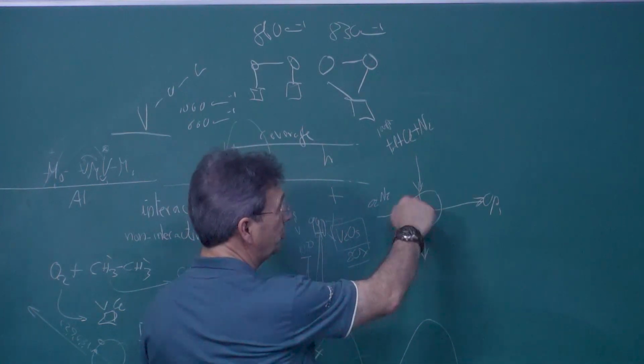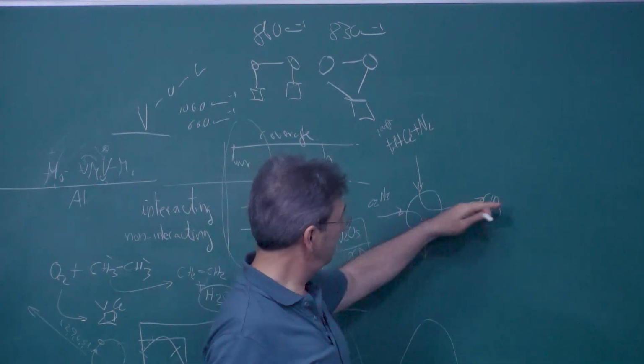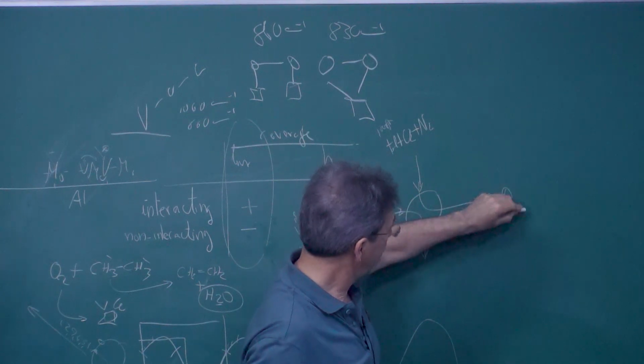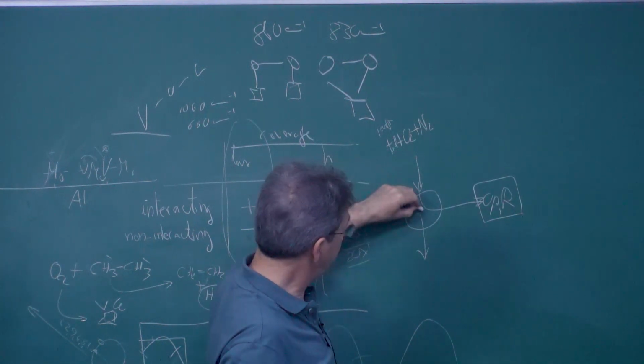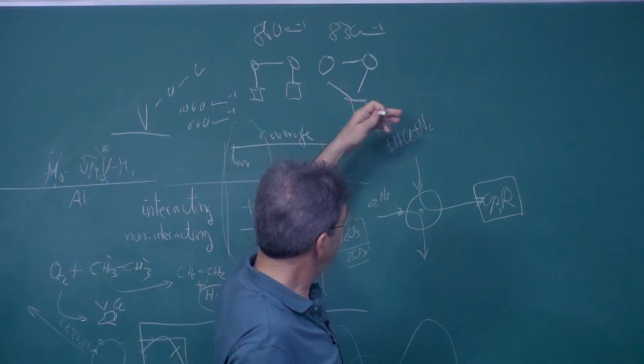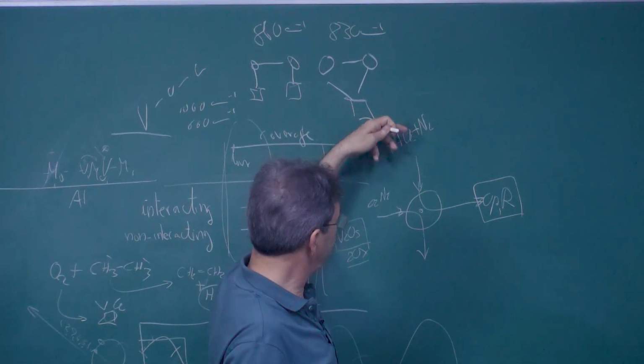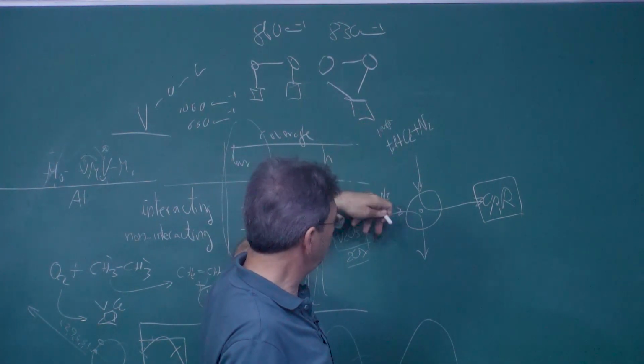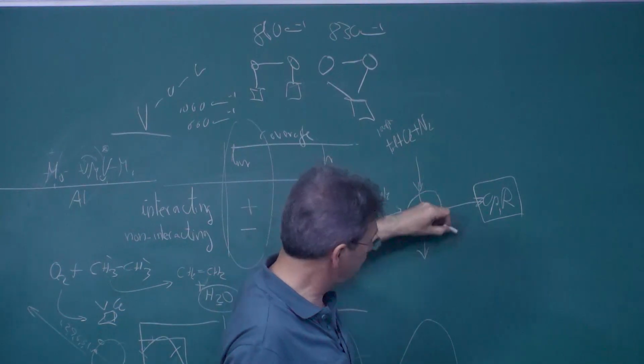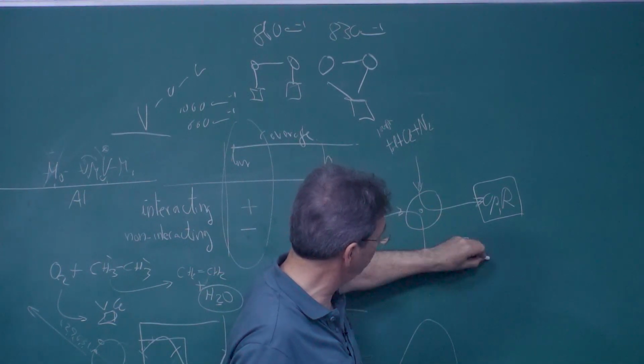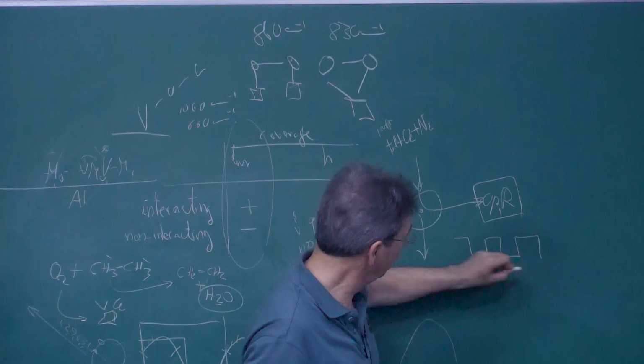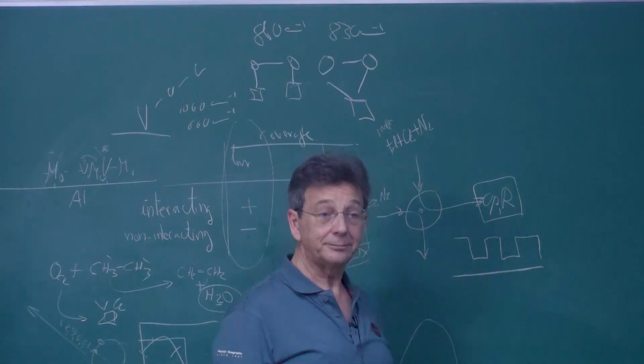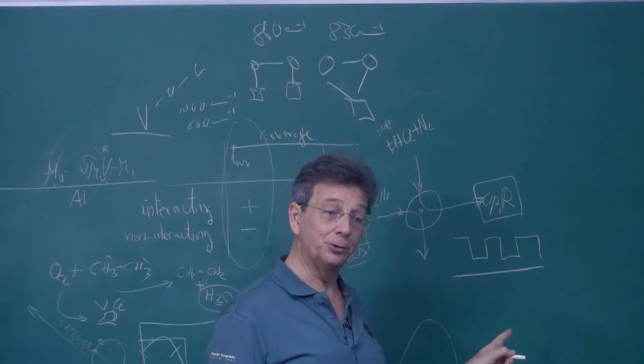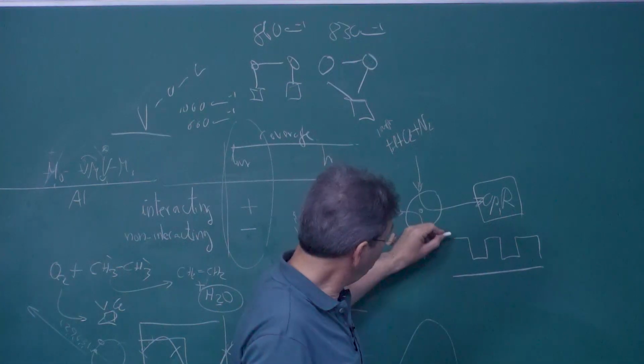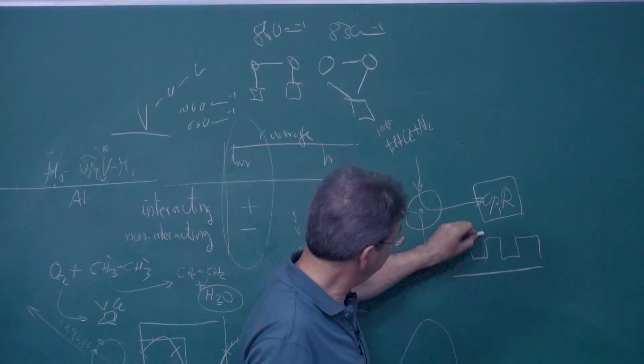And you are periodically switching. So you are feeding, and here is the reactor. So basically, by switching this periodically, you are feeding air with toluene, without toluene, with toluene, without toluene. So you make this perturbation, which is toluene, no toluene, toluene, no toluene, and continuously air. This is a periodic perturbation. What is the frequency of this cycle?